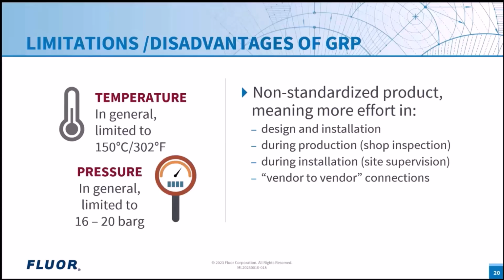Of course, GRP has its limitations and disadvantages too. Looking at the temperature in general, it is limited to about 150 degrees Celsius. Also for the pressure, there's a certain limitation compared to steel. Although, as GRP is in a lot of times used in water systems, the pressure in underground systems is normally limited to about 16 to 20 bar, which is easy to handle. Where for HDPE, for example, these pressures become a challenge, certainly with elevated temperatures.